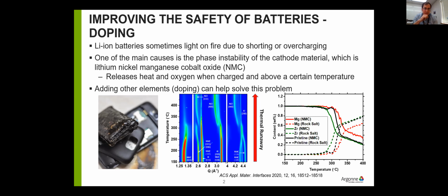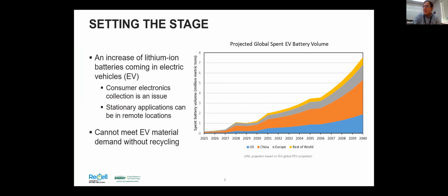Lithium iron phosphate, on the other hand: both lithium iron phosphate and iron phosphate are basically stable structures. So there's no reason for it to release oxygen, and that's why it tends not to have very much thermal runaway, but you still have reactions from the electrolytes. I just wanted to mention that to reiterate and clarify why people are so concerned about the state of charge of the batteries, because the more you charge it, the more likely it is to blow up, basically.